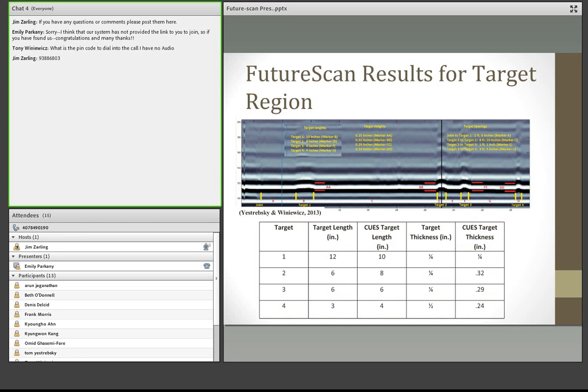So, as I had mentioned before, the pipe got installed, and then the next day we came back, and CUES came with all of their equipment, and they did the FutureScan radar scan. We also used GPR to try to locate these voids that we installed. And so what this slide shows is basically the FutureScan data for that specific region where we installed those foam targets. And a reminder, that was about the last 40 feet.